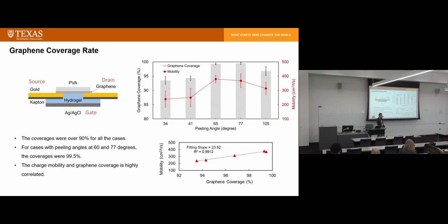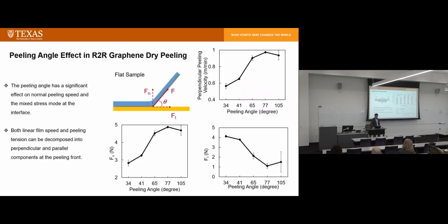And then we looked at the peeling angle effect on graphene coverage. We can use SEM to calculate the graphene coverage ratio. You can see when the peeling angle is small, it's already pretty high, above 90, around 95 percent coverage. But if you have a peeling angle at 65, 77 degrees, graphene coverage is really, really good. It's almost 100%. We also did mobility measurement. When you have larger area, graphene mobility is obviously also higher.